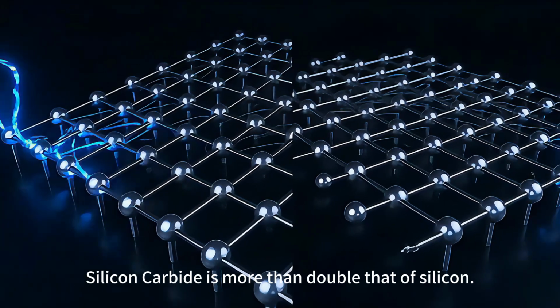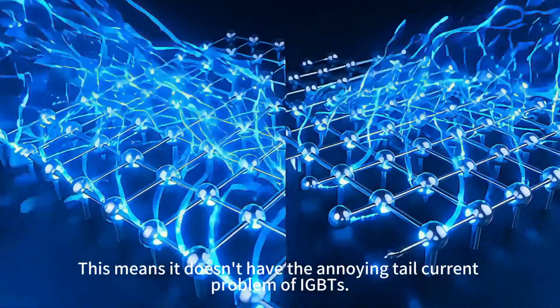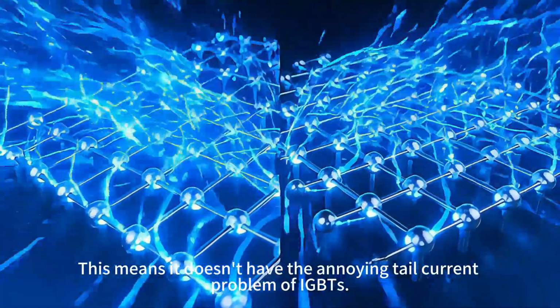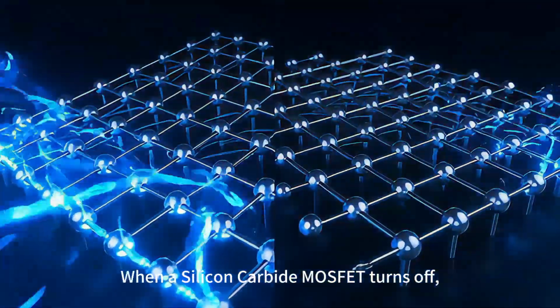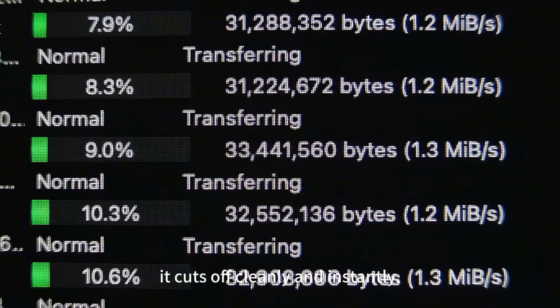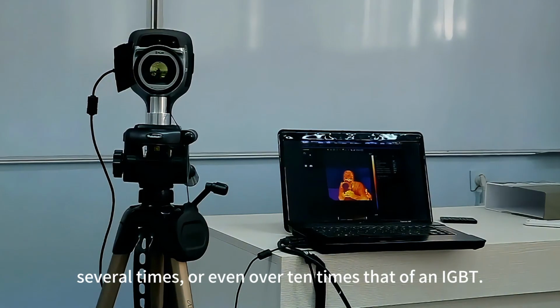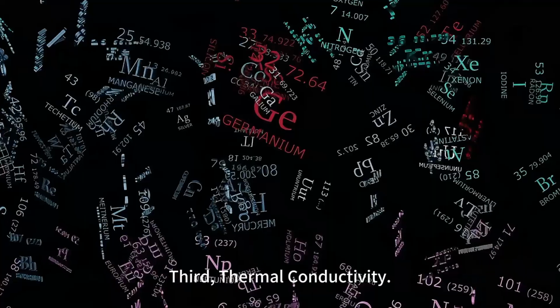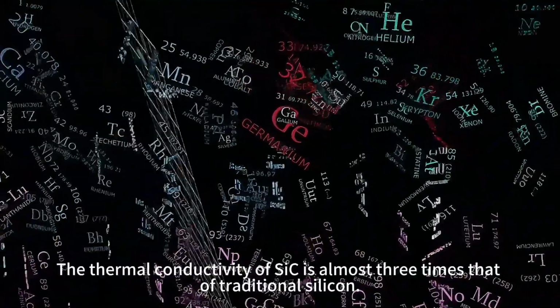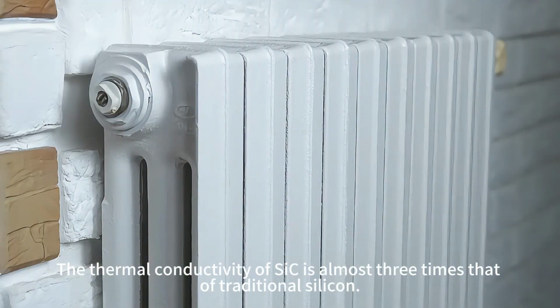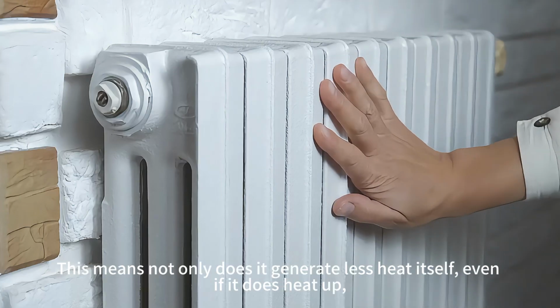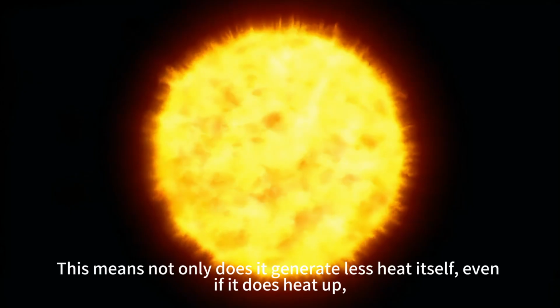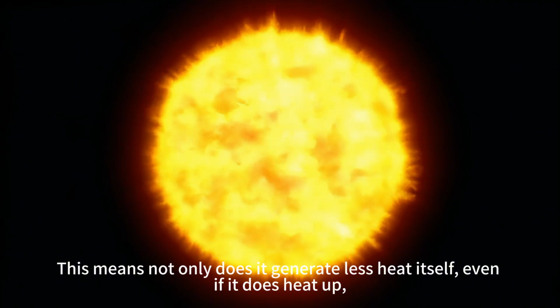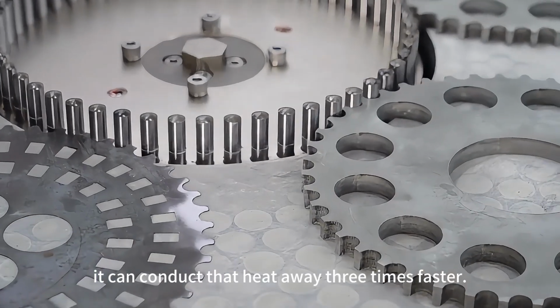Second, electron saturation drift velocity. Silicon carbide is more than double that of silicon. This means it doesn't have the annoying tail current problem of IGBTs. When a silicon carbide MOSFET turns off, it cuts off cleanly and instantly. This allows its switching speed to easily reach several times or even over 10 times that of an IGBT. Third, thermal conductivity. The thermal conductivity of SiC is almost 3 times that of traditional silicon. This means not only does it generate less heat itself, even if it does heat up, it can conduct that heat away 3 times faster.